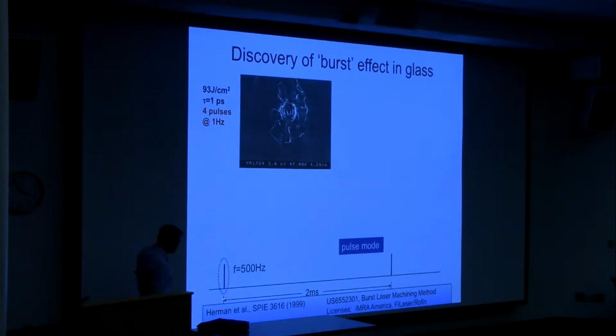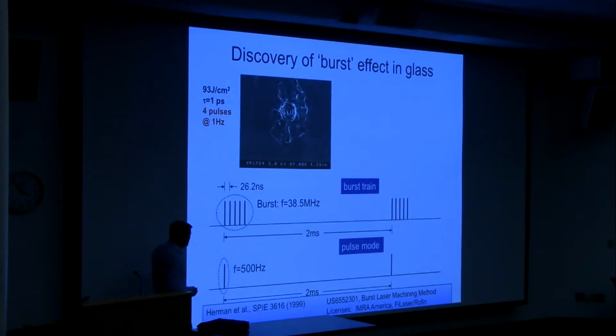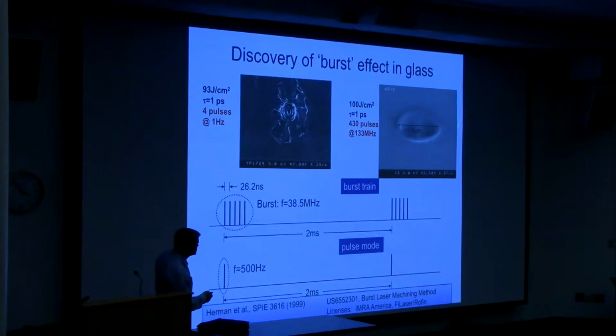This was done at a very low rep rate laser. And we had trouble finding these spots under the microscope. So out of that challenge, we thought we could apply a different mode of the laser. This custom-built laser offered bursts of hundreds of pulses in very short duration, with separation times of 26 nanoseconds. And so we thought, if we hit it with this pulse to get this, that's just 4 pulses. If 400 pulses hit that, it should be a really easy to find structure with lots of cracks. What we saw was a big structure, but there were no cracks. The funny thing is, how does 4 pulses make cracks, and this avoids cracks altogether?